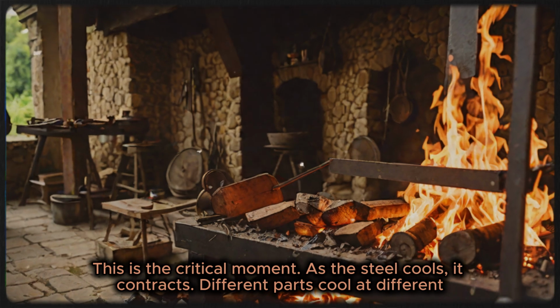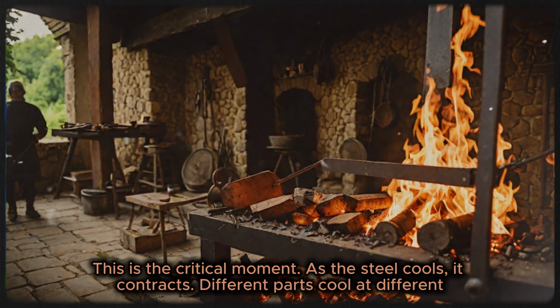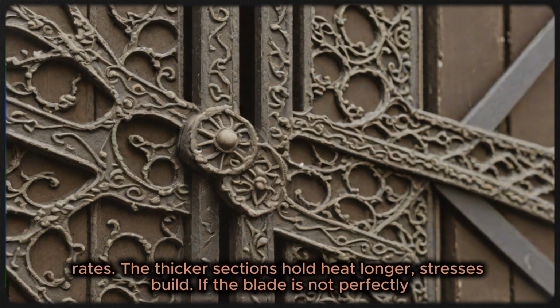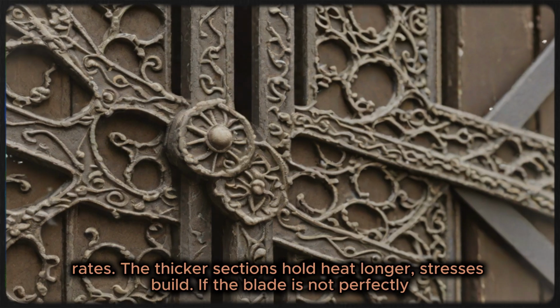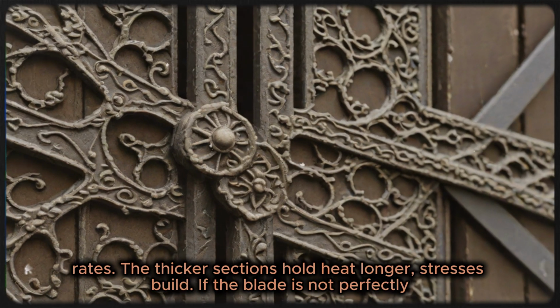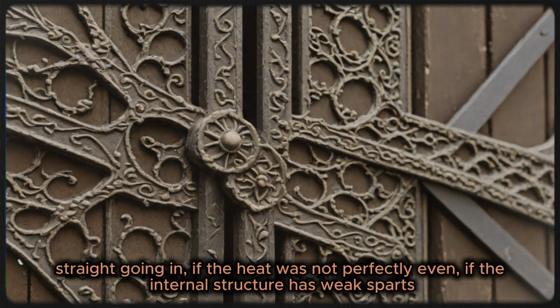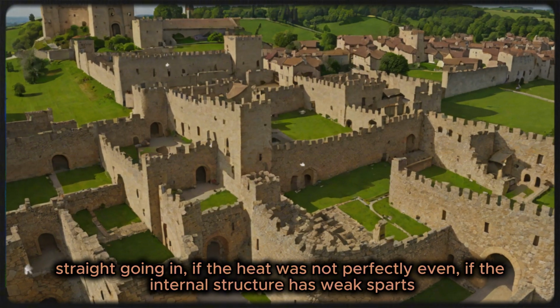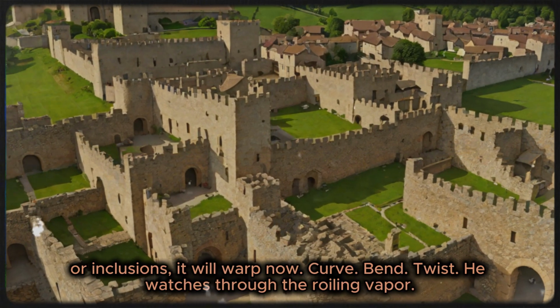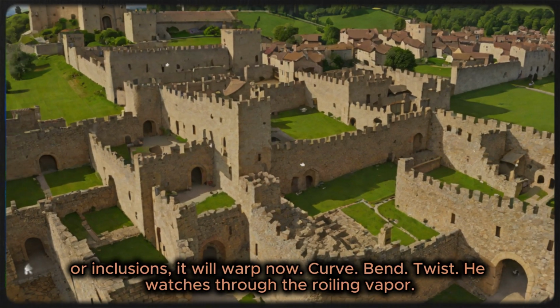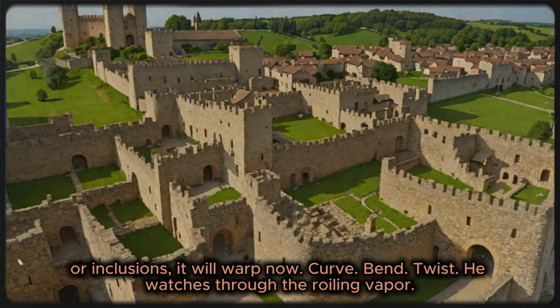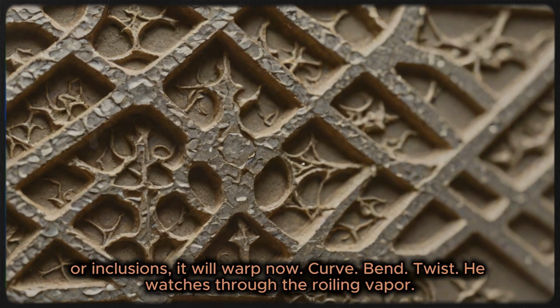As the steel cools, it contracts. Different parts cool at different rates. The thicker sections hold heat longer, stresses build. If the blade is not perfectly straight going in, if the heat was not perfectly even, if the internal structure has weak spots or inclusions, it will warp now. Curve, bend, twist. He watches through the roiling vapor.